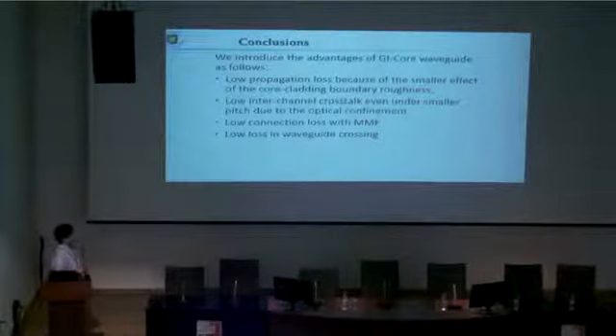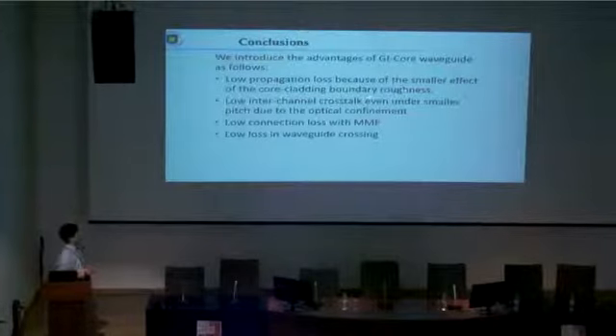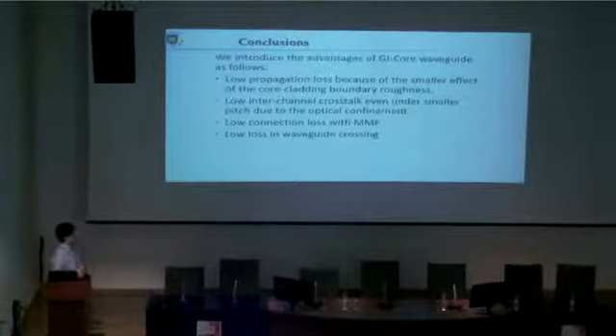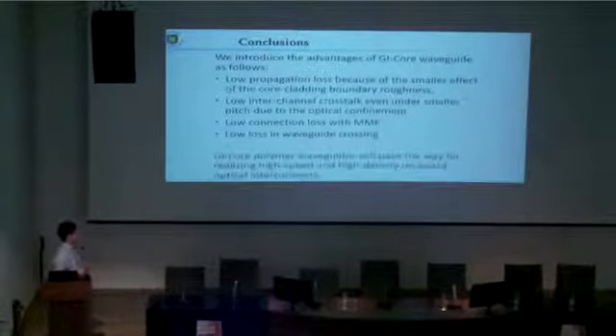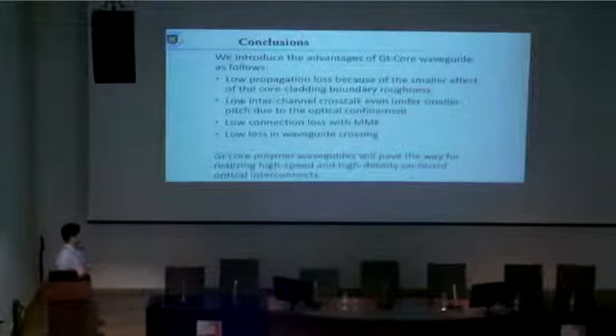So I'd like to conclude my talk. We introduced the advantages of the graded index core waveguide as follows. Low propagation loss because of the smaller effect of the core-cladding boundary roughness. Low interchannel crosstalk even under smaller pitch due to the optical confinement in the core. Low connection loss with an MMF, multimode fiber, and low loss in waveguide crossing. So GI core polymer waveguides will pave the way for realizing high speed and high density onboard optical interconnects.